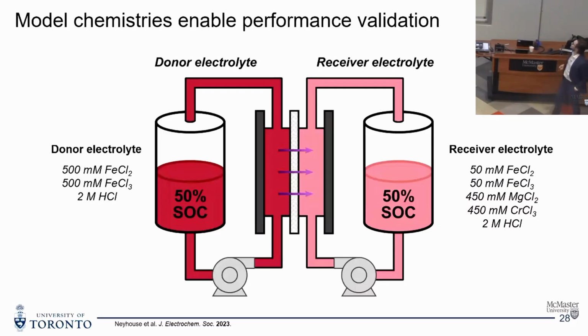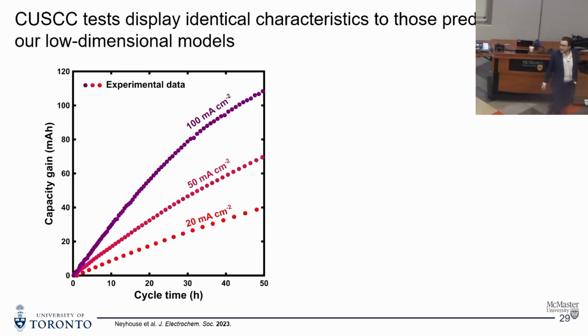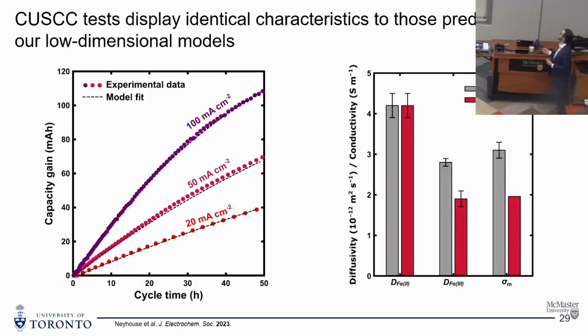So we set this up and went ahead and ran it in our lab with Nafion 117, a kind of classical electrochemical membrane. And we see exactly the behavior we would expect from our mathematical models. Of course, I showed you parameters that were similar to what we saw in our experimental techniques. And we see that same behavior. And additionally, because we have a computationally fast mathematical model, we can also use that to easily fit this data very quickly. And if we fit that data, our model fits this performance very well. We can extract out the key transport properties we care about, our diffusivity of both of our species and our conductivity. And that matches pretty well with what we measure ex situ, albeit there are some differences, and some of these differences evolve over time with our performance. I won't go into that.